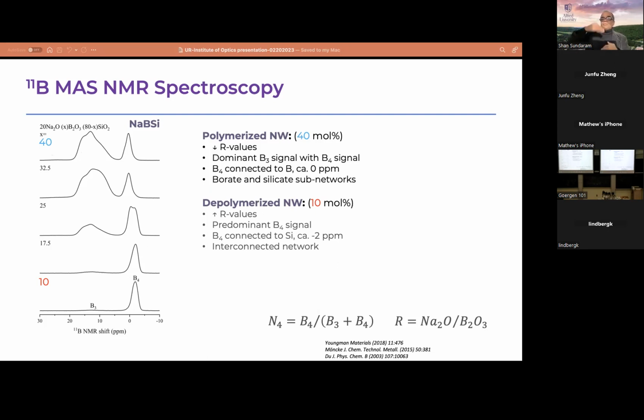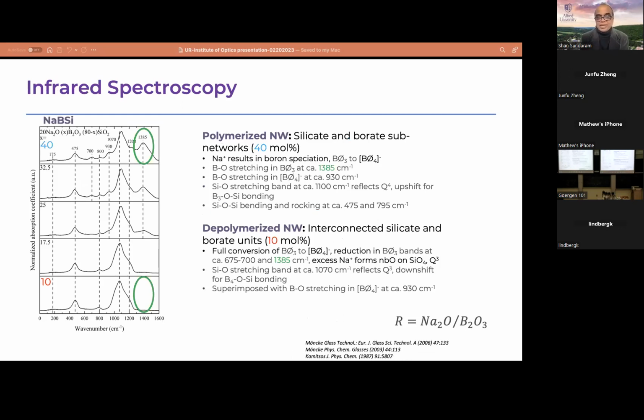So what happens is when we keep adding more and more boron, it forms additional network species inside the glass, getting more and more polymerized, more and more connected. While we are reducing the boron, it gets more and more open, depolymerized. We see a similar trend in all our glass families. So I'm showing you now infrared spectroscopic data. We look at various bands, and we know that all those bands are related to specific glass structures. I'll walk you through 2 or 3 spectra. Once again, I'm showing the compositions from 10 mole% boron all the way to 40 mole% boron, and I will point out various features in these bands and how we can interpret the structure, what is inside the piece of glass. For example, if you look at the 1385 inverse centimeter band, you can see the spectral shift with composition.